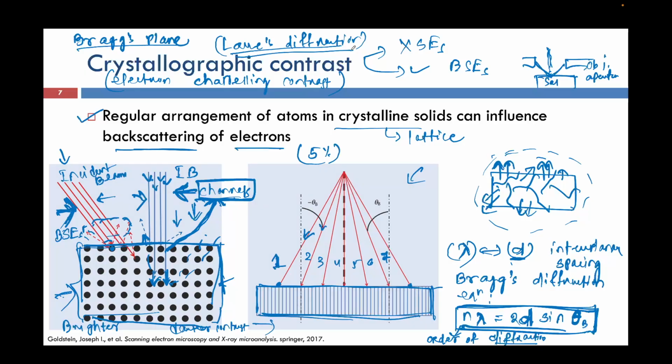So this Laue diffraction, which is based on the scattering phenomena, has been oversimplified by Bragg's equation. There are three Laue laws: the first, second and third law. When all three laws are simultaneously met, only then does the condition of diffraction take place. Bragg oversimplified this, so that when a beam of energy falls onto a material and reflection or scattering happens, we consider it in a two-dimensional manner, whereas Laue diffraction describes the scattering in a three-dimensional manner.